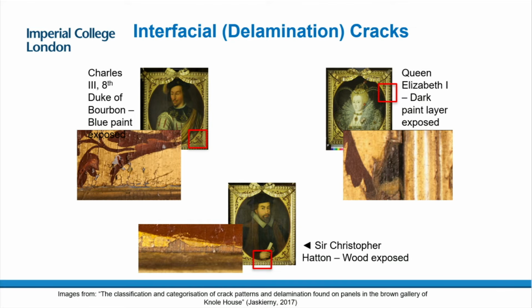Basically, this is paint flaking off, like you see here in the gilding of Charles III. So the gilding has come off and exposed the original blue layer underneath. And the same here with Queen Elizabeth. You've got all this piece of the gilt, the gold bit, that came off, and we have the black paint layer underneath. Here we have all the layers have come off, and you expose the wooden panel underneath.